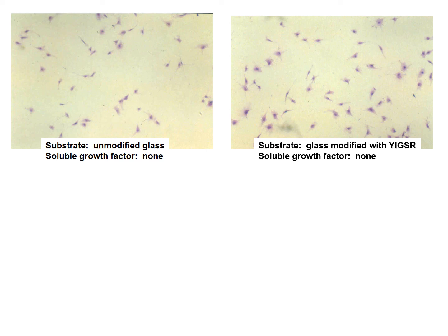Comparing the 2 frames, left and right, we see that when we have modified the substrate surface with the adhesive peptide, there were many more cells which adhered on that particular surface at the same time interval, 72 hours after the inoculation of the surface with the cells.